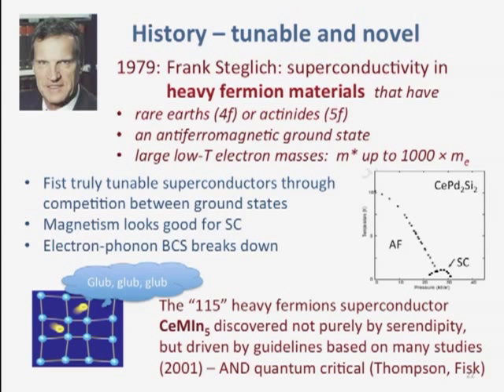They also have very large, they're called heavy fermions because the m star is up to 1,000 times the free electron mass. And that is not explained by the band mass. If you've taken solid state physics, you know that m star is calculated by 1 over the curvature of the band structure. You're not going to get 1,000 m star that way. So it has to do with a certain interesting kind of hybridization. The bottom line, it's a strong electron correlation effect, not dictated by the band structure.